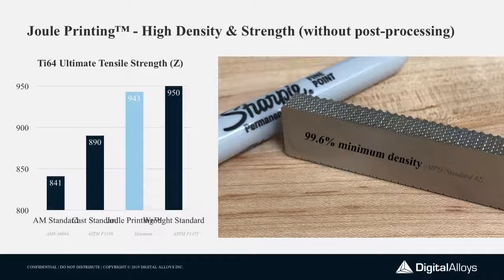So the colors don't come across very well, and this formatting looks to be a little weird on this slide. But basically, you can see the bar that represents the joule printing Z strength. And that's typically the most challenging orientation, right, to pull the part in across the layers. But we're seeing very close to wrought properties from the minimum of a fairly large sample of coupons. So we're seeing not quite wrought yet, but we're getting there. We're still improving and refining the process and the software. But we're seeing very close to wrought properties right out of the printer, without any heat treatment, without any hipping, which is pretty standard for printing titanium with other processes. So we're excited about that.